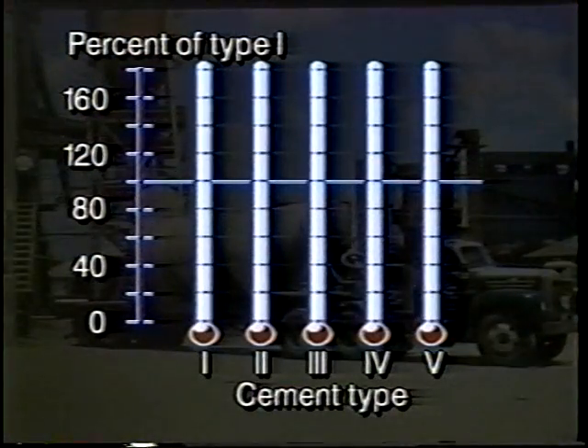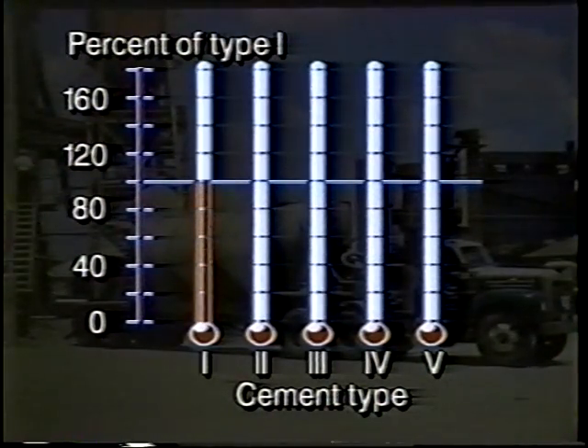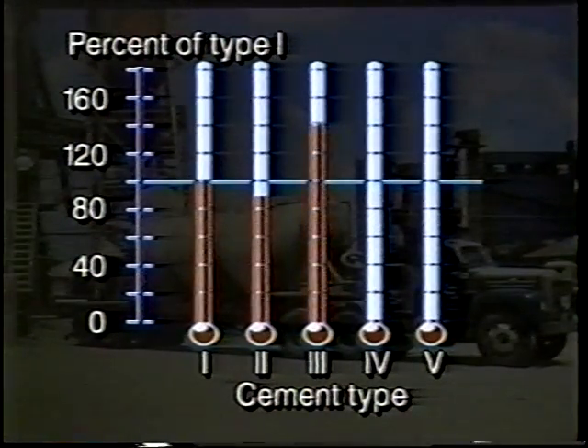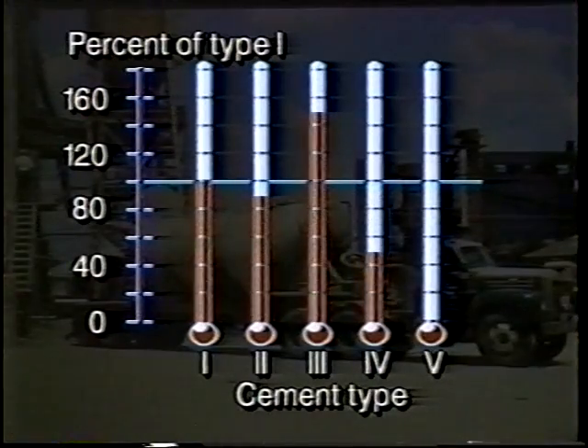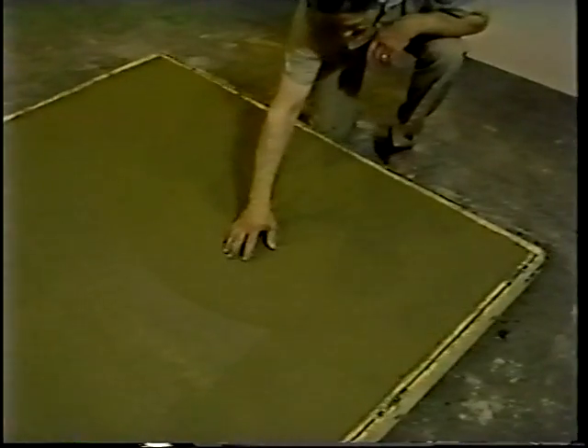The approximate amount of heat generated during the first 7 days based on 100% for Type 1 Portland cement are Type 2, 80 to 85%, Type 3 up to 150%, Type 4, 40 to 60%, and Type 5, 60 to 75%. The rate of hydration determines the setting and hardening time of the concrete mixture. Gypsum added to the cement regulates the initial rate of hydration, although other factors can influence this rate as well. As we have noted, concrete needs moisture to hydrate, harden, and gain strength.